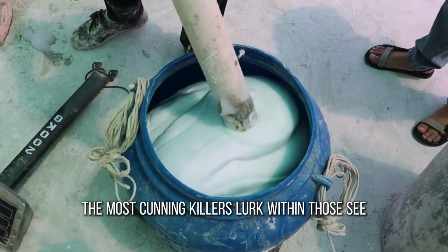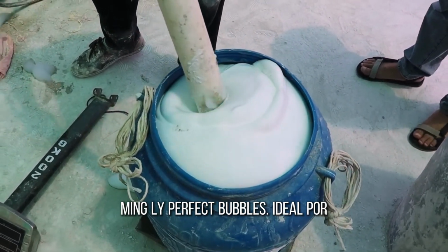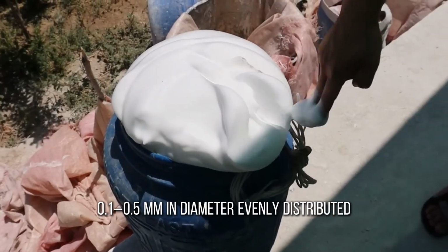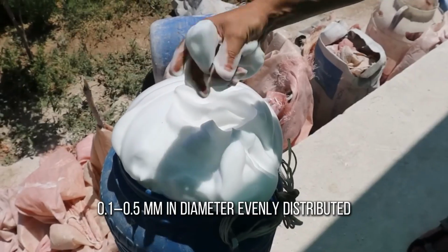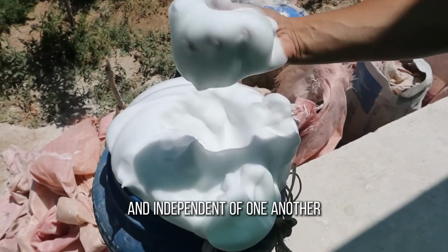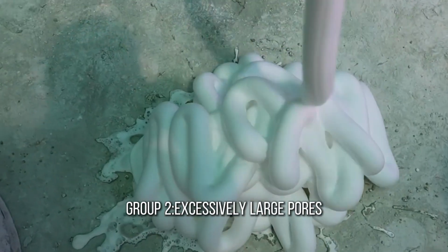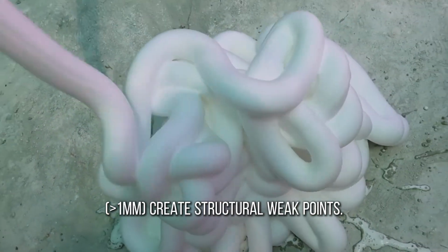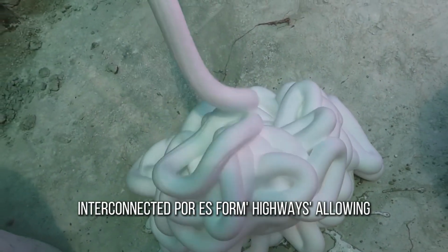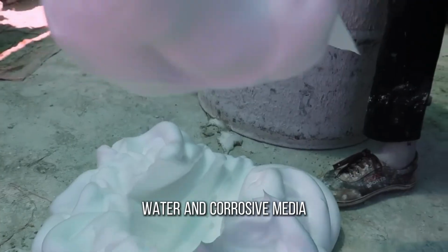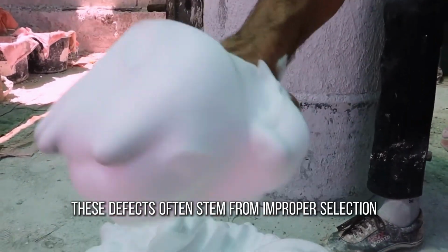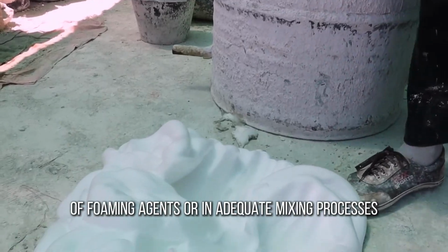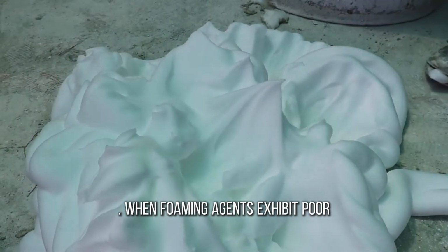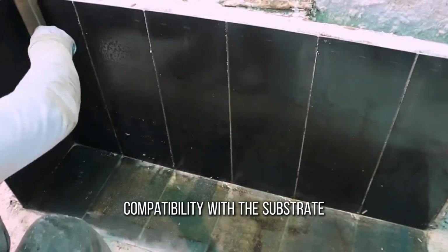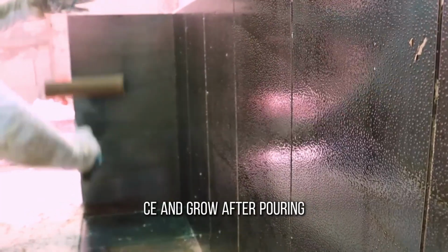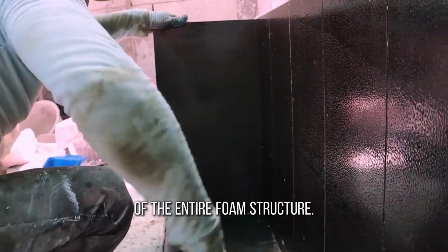The most cunning killers lurk within those seemingly perfect bubbles. Ideal pores should resemble the first set, 0.1 to 0.5 millimeters in diameter, evenly distributed and independent of one another. But problems often arise. Group 2, excessively large pores over 1 millimeter, creates structural weak points. Group 3, interconnected pores, form highways, allowing water and corrosive media to penetrate unimpeded. These defects often stem from improper selection of foaming agents or inadequate mixing processes. When foaming agents exhibit poor compatibility with the substrate, bubbles continue to coalesce and grow after pouring, ultimately compromising the stability of the entire foam structure.